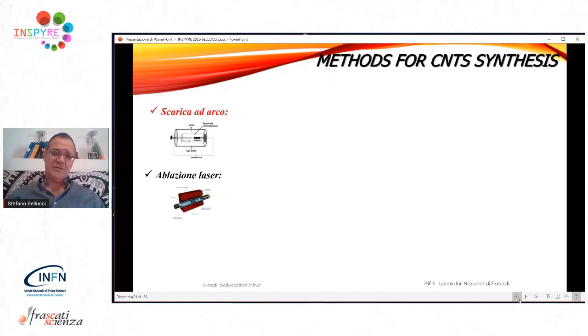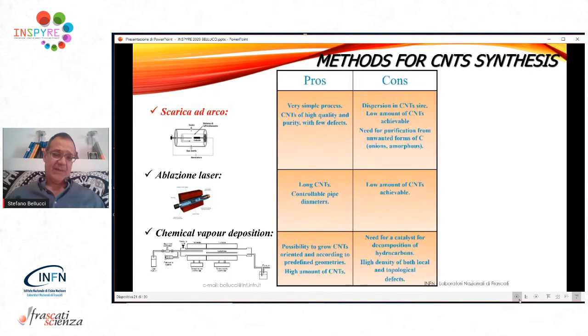How do we realize these carbon nanotubes? Arc discharge, laser ablation, chemical vapor deposition. So we have in our lab arc discharge and chemical vapor deposition. The arc discharge is a physical method based on voltaic arc. The chemical vapor deposition is a chemical method, obviously, that is based on a precursor that is a gas. It's a carbonaceous gas that is normally decomposed at high temperature, ranging from 600 up to 1000 Celsius, more or less, depending on the type of material you want to obtain. And the decomposition of the gas, for instance, methane, CH4, you decompose it and the carbon atoms become available to rearrange in a desired structure, for instance, a carbon nanotube or graphene. All this can be engineered.